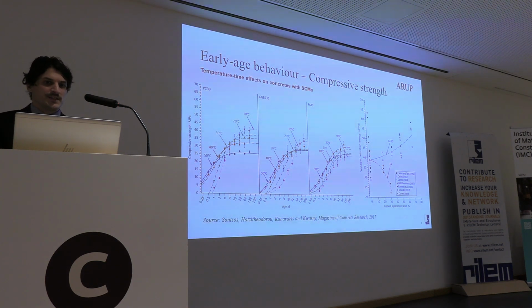And for temperature sensitivity, there is a more scientific term for how we can express that. We normally express it as an activation energy, which is an indicator of the temperature sensitivity of a particular mix. We can see that GGBS, which is slag, is normally more temperature sensitive than ordinary concrete, while fly ash is less temperature sensitive. And that really affects the early age behavior overall, not just the strength, of the cementitious materials that we're investigating.